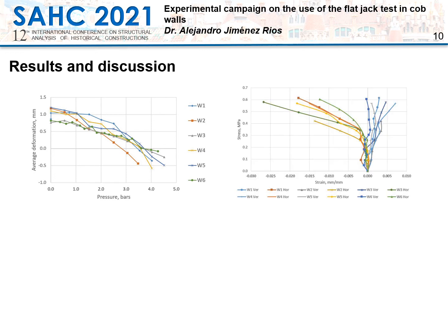This figure presents a summary of the stress-strain curves obtained from the double flat jack test. The positive values of strain represent a decrease of the distance between control points, whereas the negative values of strain represent a separation between the control points. Therefore, the stress-strain curves plotted to the right of the zero value correspond to the strains of the vertical control points, and those plotted to the left correspond to the horizontal control points.